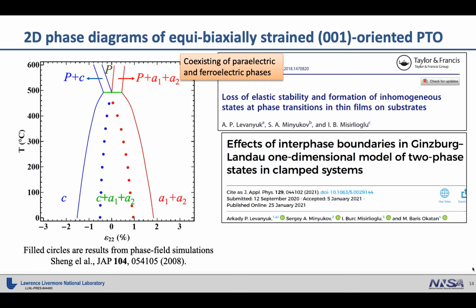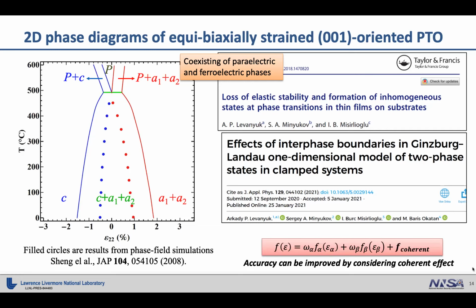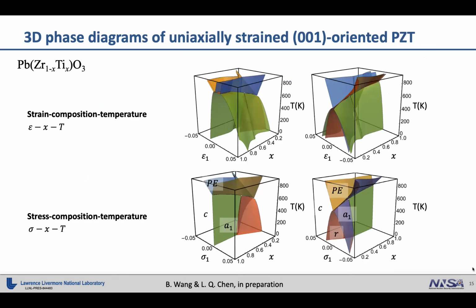and ferroelectric phases. Another finding is that there's a large deviation from the phase field simulation for the phase boundaries. To improve this, we can incorporate another term, an interaction term between the coexisting phases, to account for this coherent strain effect. But I won't go into details in today's presentation.